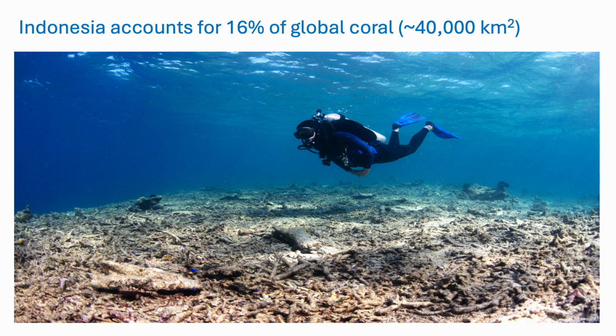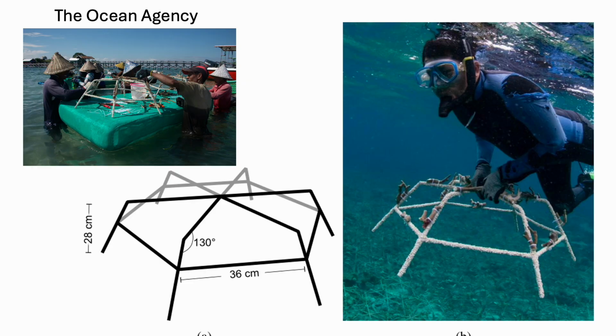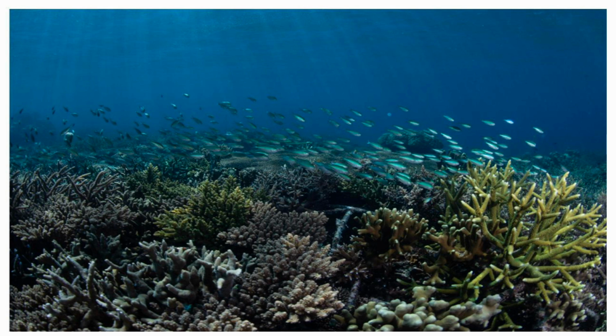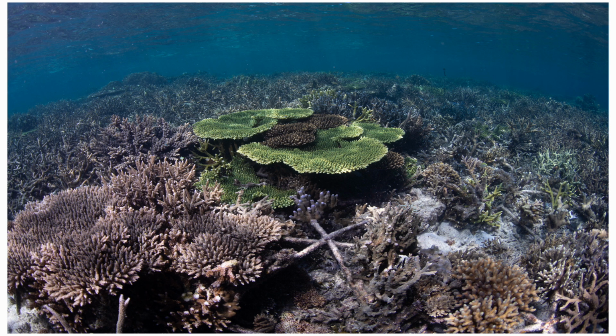Well, you make these steel frames out of the cheapest possible steel, ordinary reinforcing bar bent into shape, and you attach live coral to parts of that frame structure, and then you just place it on the seabed. And the density of the steel means that it's not washed away by storms, etc. And look at the next picture, which is really quite remarkable. You can see that the coral reef is completely recovered, and if you look carefully you might see remnants of the steel frame, but here's another picture which shows the steel frame more clearly.